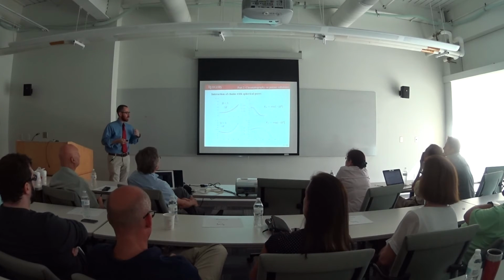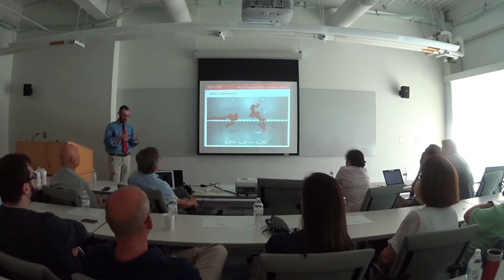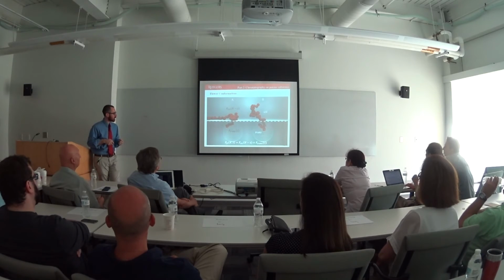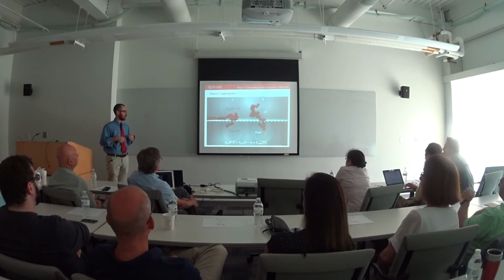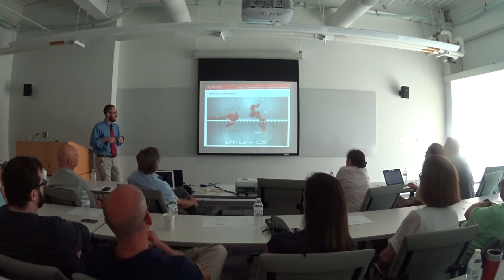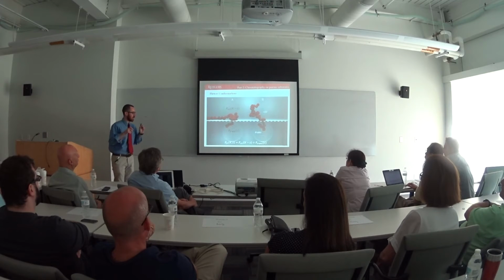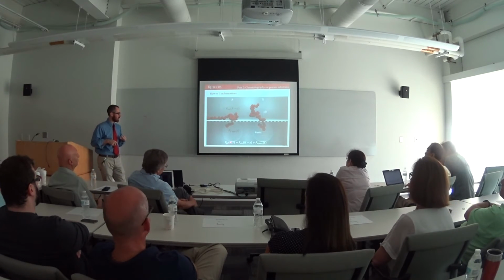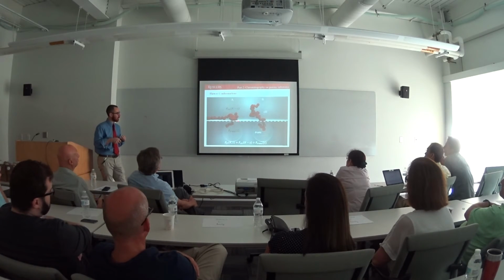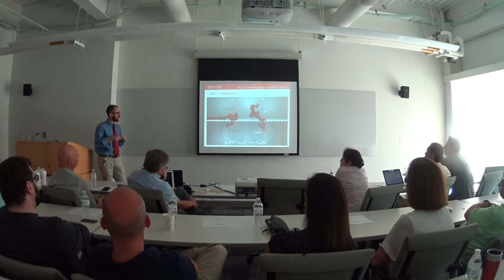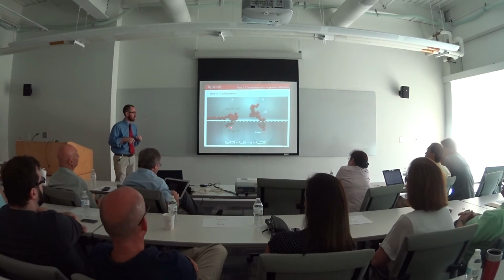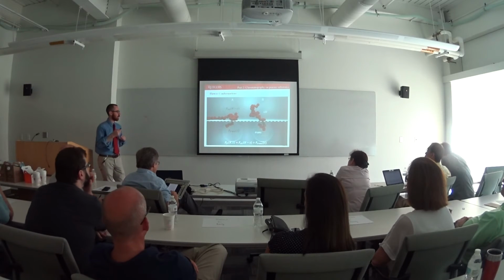However, we can introduce another mechanism that gives us another way to look at it. So, like I briefly talked about earlier, we can introduce the case of flower conformations. So, again, a flower conformation is a chain which is partially inside and partially outside of the pore space. And the free energy of this chain is composed of two parts: a cis part, which is the external, and a trans part, which is inside the pore. The free energy of this type of chain is the sum of those two parts. This letter S is the degree of translocation of the chain, which is just the number of beads which are inside the pore.